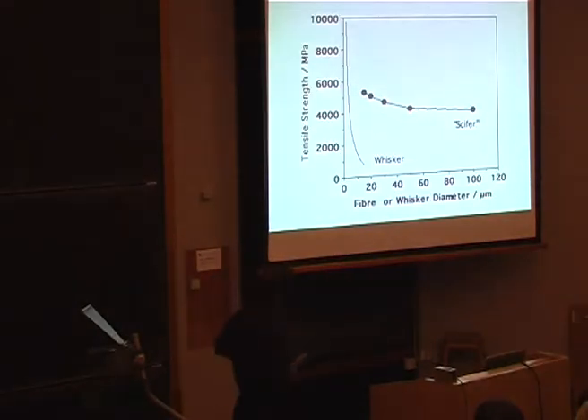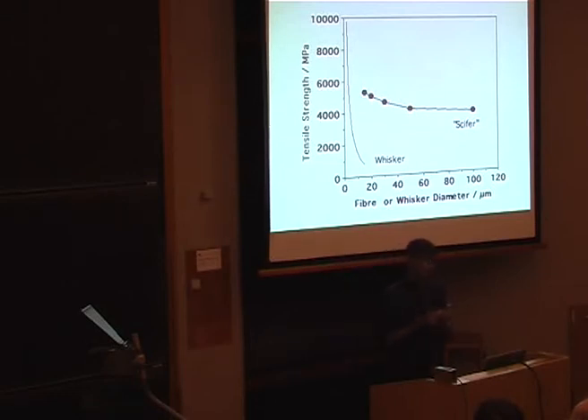Now, that makes it very insensitive to size compared with those single crystals that I showed you earlier. So that's a good thing, that when we introduce strength by deformation, we can produce things which are insensitive to size. The problem is that you have to put in this severe deformation, and that means that you're restricted in the shape of the product you can produce. Now, there are processes like equal channel angular pressing where you can maintain the shape, but nevertheless, those are very expensive processes, and really for niche applications.